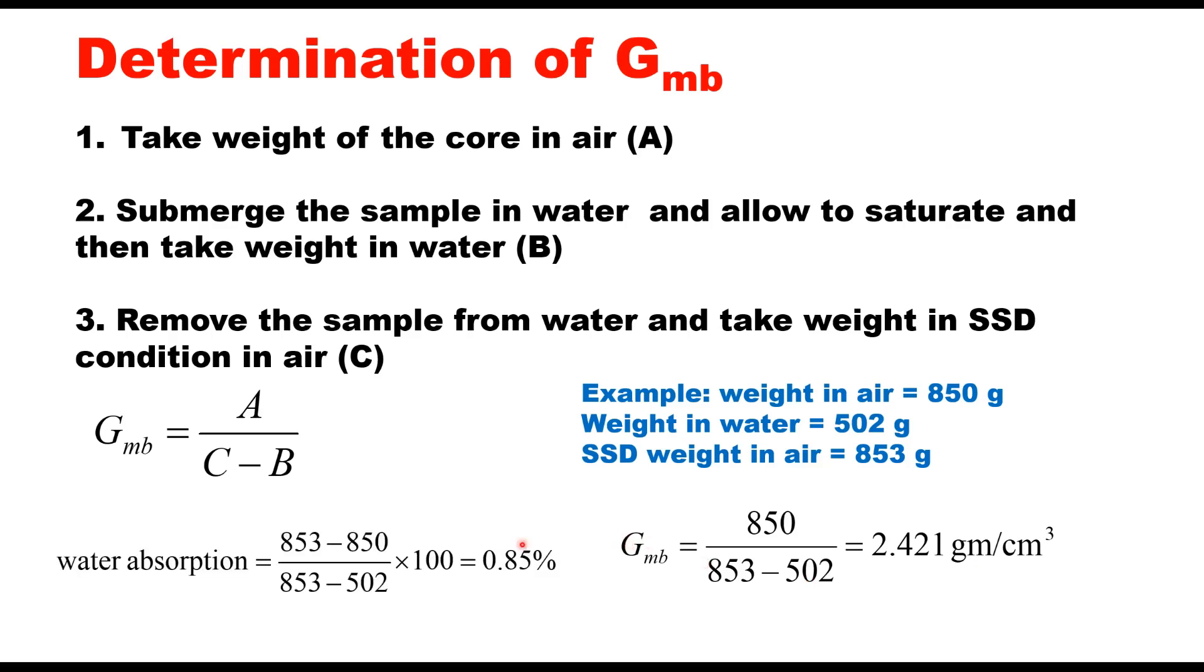Water absorption can also be estimated. The water absorbed by the sample is the difference in the weight, that is 853 minus 850. So 853 minus 850 upon the same volume of the sample, that is 853 minus 502, and that is 0.85 percent.